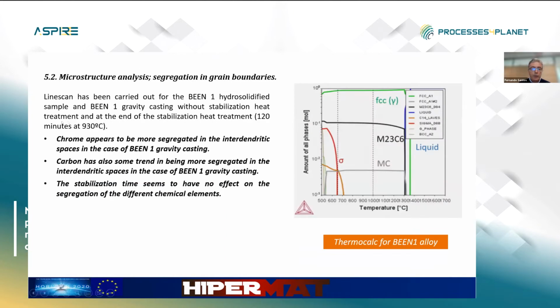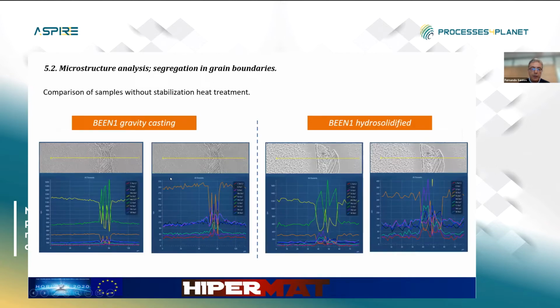If we take a look at the segregation, we have made line scans to check it. We checked that chrome is more segregated in the gravity castings, whereas it's less segregated in the case of hydrosolidified. Carbon also is more segregated in the dendritic spaces in the case of gravity casting. And the stabilization time has no effect on the segregation. So this is what we can see in the next pictures.